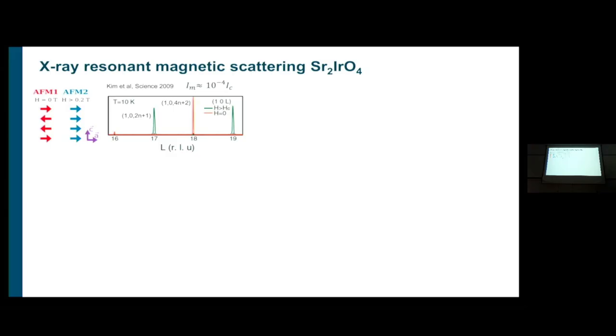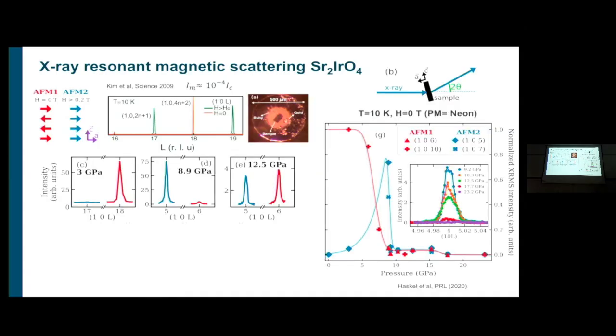And because you have these different periodicities of these arrangements, the magnetic Bragg peaks have different selection rules or different symmetries that come into play. And you see that there are magnetic peaks in zero field. The orange is 1-0 even peaks, and when you apply a magnetic field, it's 1-0 odd peaks. And we are looking at the antiferromagnet in zero field. I'm not going to apply a magnetic field, so I'm supposed to see 1-0 even peaks. So here is the experiment. These are 17, 18 is the L index, and then 5, 6, 5, 6. When we go to low pressure, we don't see the odd peaks, we only see the even peaks, as we expect from this stacking of moments.